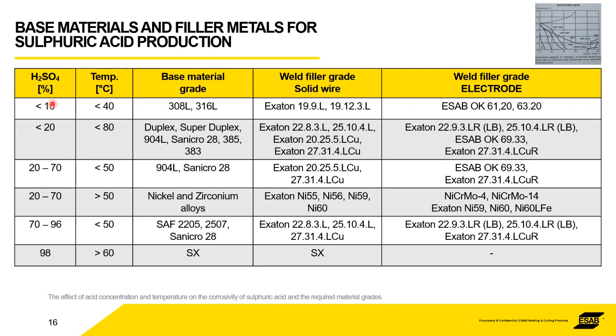So if you have sulfuric acid that's less than 10% strength, and it's less than 40 degrees, then even materials such as standard austenitic stainless steels like 308 and 316 are suitable. So they're suitable for the fabrication. And obviously we've got solid wire filler grades as well as electrodes, the topic of this webinar.